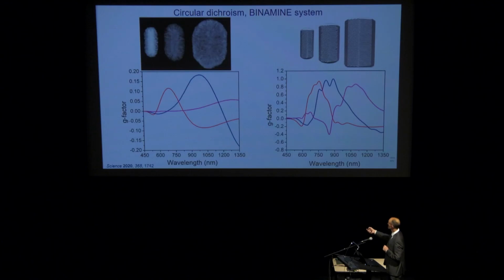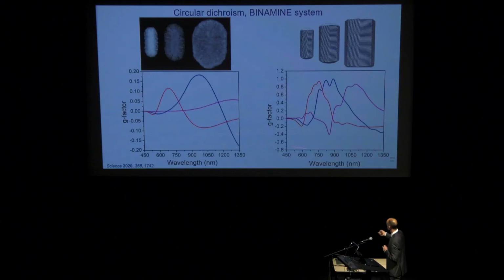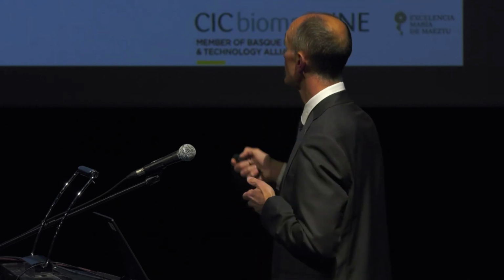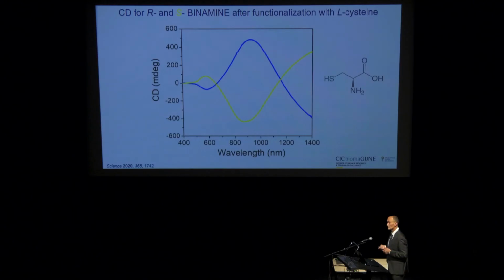And not only that, by tuning the dimensions of these grooves, you can tune the position of the circular dichroism peaks. And you can also correlate it with theoretical simulations of the interaction of light with models that look like our particles. And also, if you use the different enantiomers of the co-surfactant, you can obtain mirror optical activity bands, circular dichroism, which confirms again the templating effect.